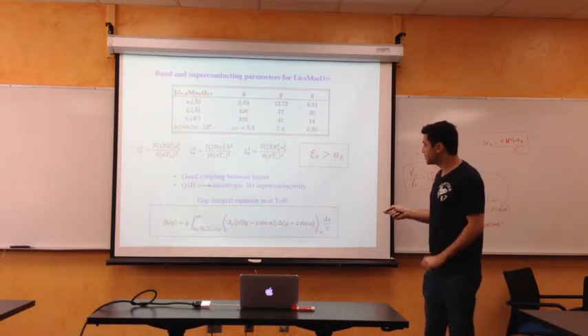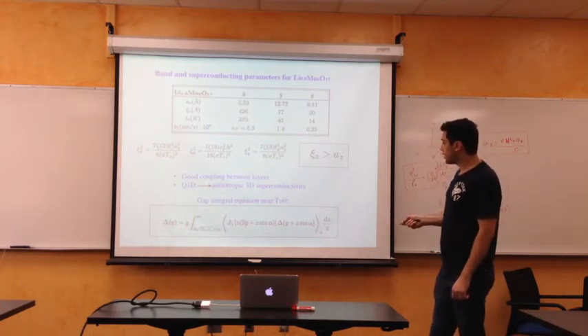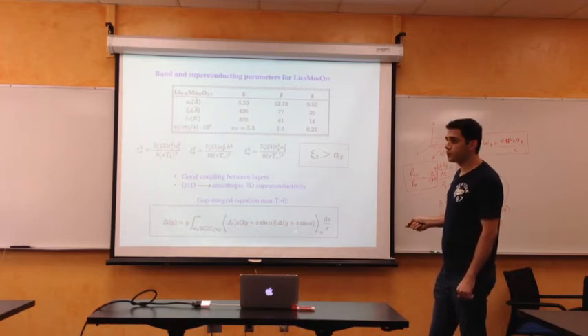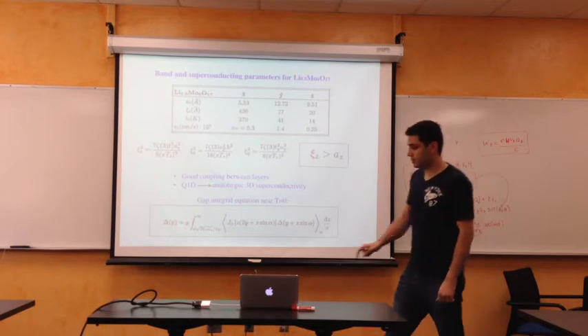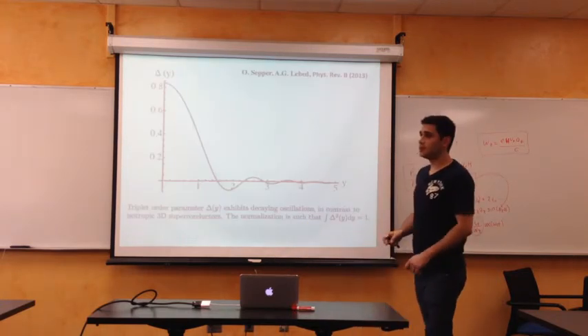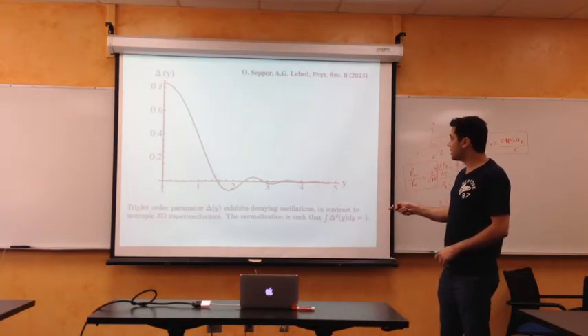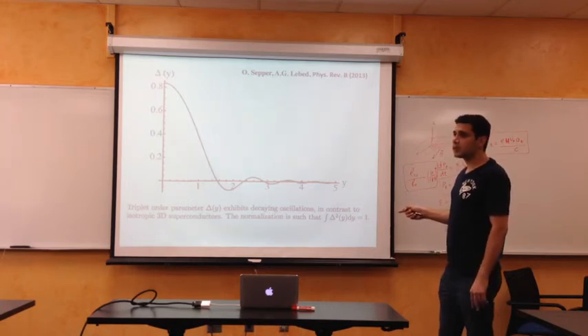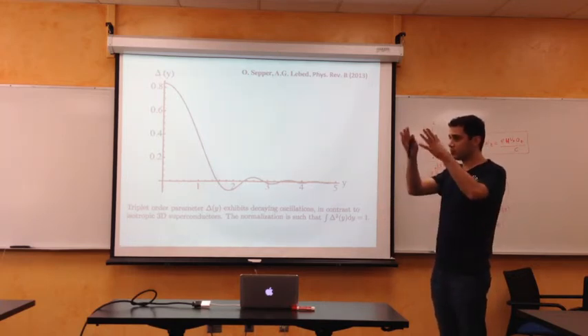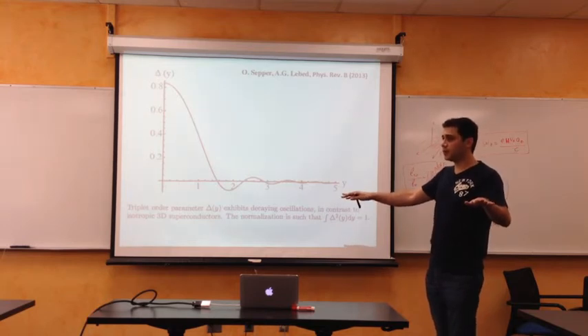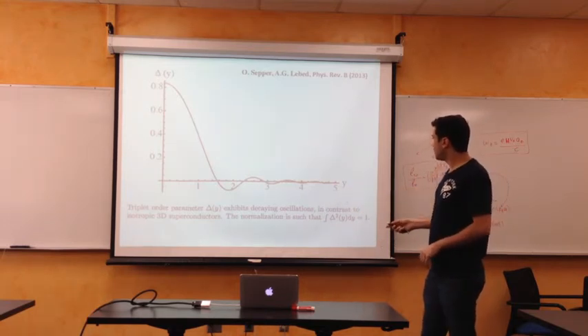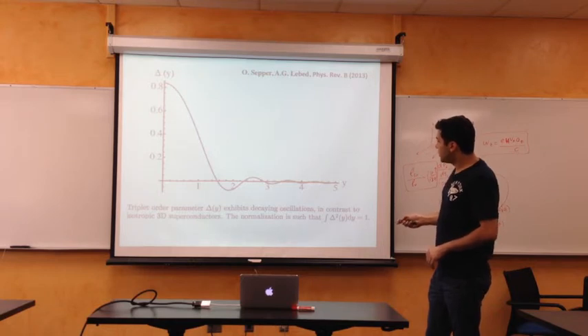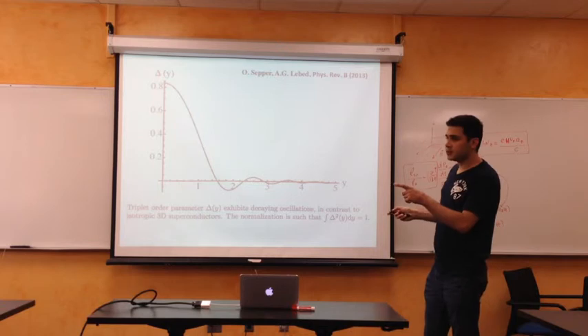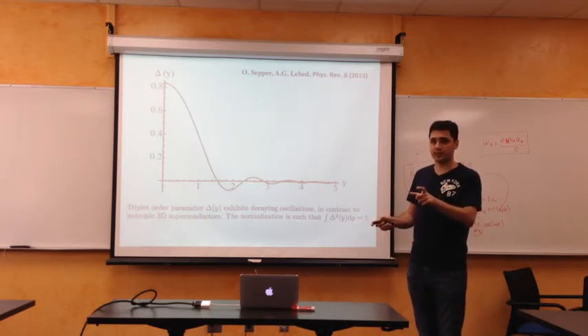That allows us to reduce the gap integral equation to this form and subject it to numerical analysis this way. The solution is this. It clearly shows unconventional behavior. This is nothing like the Ginzburg-Landau case where you have Gaussian smoothly decaying exponentials. So you have decaying oscillations here. The scale of these decaying oscillations, the distance scale, is in fact on the order of the coherence length.